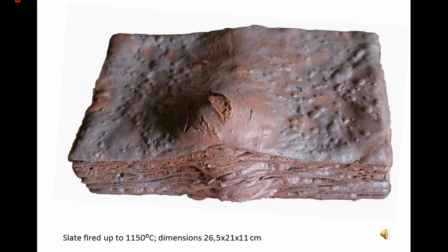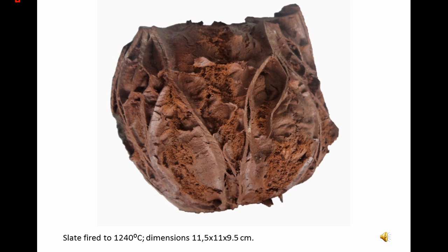Fire up to 1150 C. The pieces of pyro-expanded black slate, in case they are put all together, become bonded to each other. Hence, when they are placed inside the kiln, it's important to separate or isolate them from the kiln walls and from the kiln furniture. Fired up to 1240 C, the pervious skin is ripped apart, showing the sandy and porous texture of its internal spongy mass.